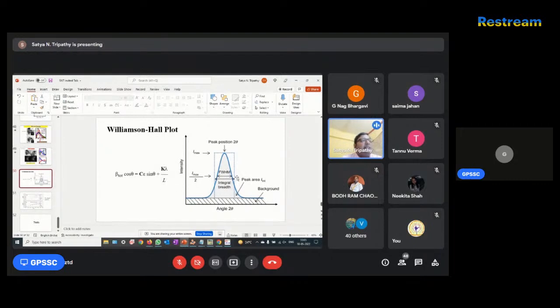What we do, we basically calculate the FWHM of the peak. So beta is the FWHM. By fitting with any software like Origin, you can calculate, and from the intercept you can calculate the crystallite size, and the strain you can calculate from here.